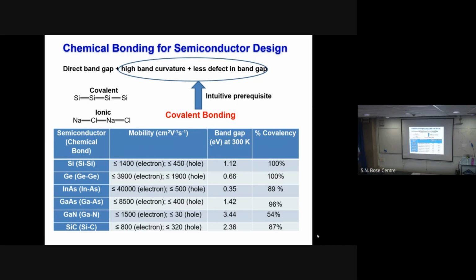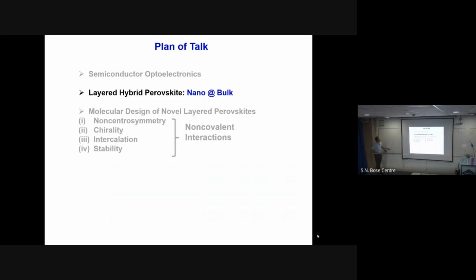No, the problem is that gallium nitride, for example, is a polar material, so you have polar optical phonons. You mean optical phonons? Yeah, those can kill mobility very significantly. So you can think of the deeper physics here. Yes, but that's how I also keep learning.